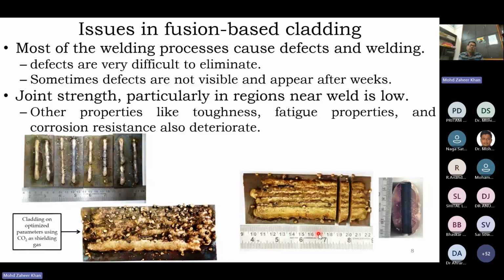So we tried the process of gas metal arc welding, where a spool of copper was run through the GMAW torch, and an arc was initiated at the end of the copper. Such layers of material were attempted in the first attempt so that we could optimize the process parameters. Now remember, copper has a very different electrical conductivity, and thermal properties are also very different. Producing an arc and the formation of droplets in arc welding of copper was also something new, but we could establish the process and develop beads of desired profile, as you can see in some of these figures, and then subsequently several beads were placed one next to the other,